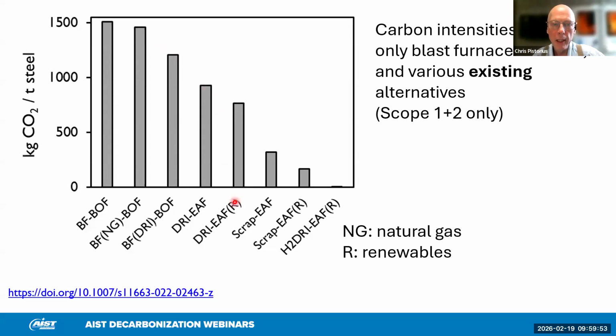If you use renewable electricity, one cuts out around 140 kilograms. If you use scrap, we're at around 300. If you use renewable electricity, again, you have that approximately. And ultimately, if one uses hydrogen DRI in an EAF with biocarbon and renewable electricity, it's very close to zero. There's a little bit of carbon needed for arguably carburization of the material. So these are using existing technology and a tweak on existing technology in the last case.